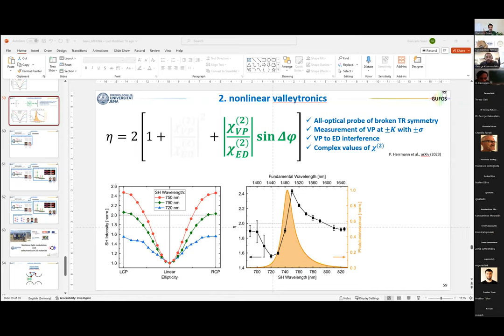as I said, the shape that we read here is the interference between the intrinsic response. So we can do the following. We can assume that the electric dipole response, the response coming from broken space inversion symmetry, is mainly imaginary, because we know that when we are close to a resonance, the refractive index becomes almost purely imaginary. And this will be similar to the derivative of the absorption. However, this is not exactly the case because the exact shape of this will depend on the quality of the material and on the substrate. And this comes directly from the Kramers-Kronig relations. And this is something that we did not calculate, right? We have this material, we have the photoluminescence, we did not go in details up to the Kramers-Kronig relation.